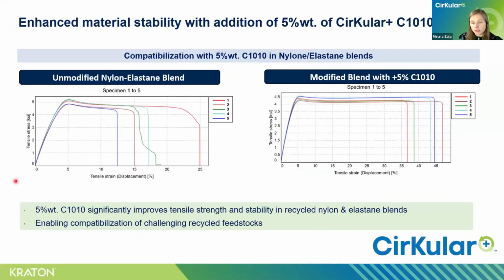So here's another data set. On the left, we see the tensile behavior of the unmodified nylon elastane blend. And here we are still talking about the same blend with recycled material, which was in the 76:24 ratio. The variability across specimens highlights the instability of the material, making it unreliable for consistent product performance.